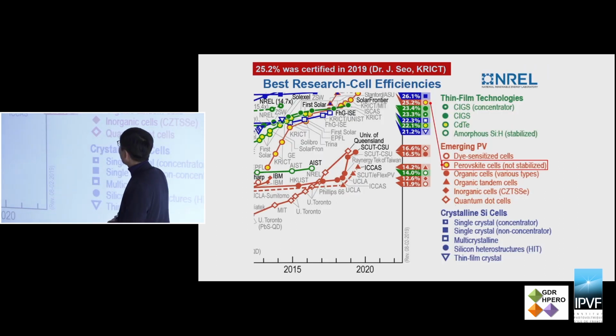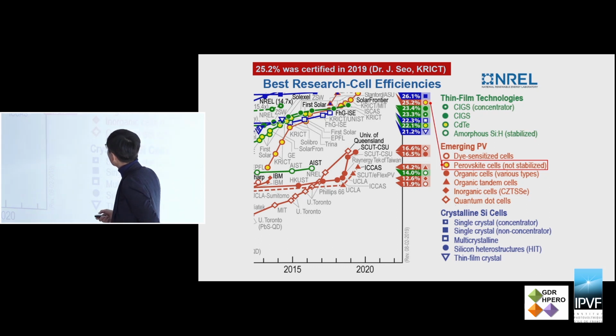Well, now the perovskite record efficiency was 25.2%, which was achieved by Dr. Jang Won-seo from the KRICT in Korea. This is the Korean Research Institute of Chemical Technology. And you see here it is very close to even the record efficiency of silicon.